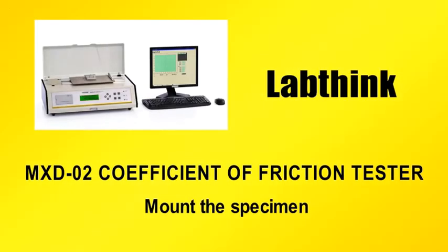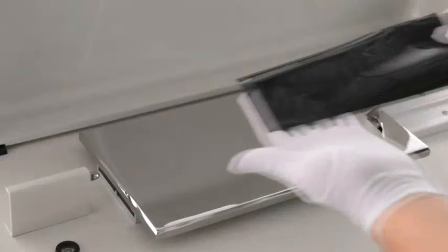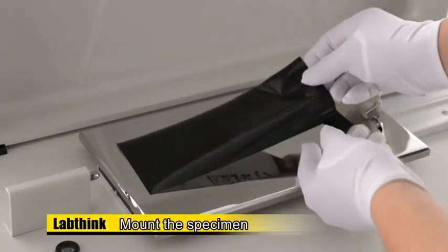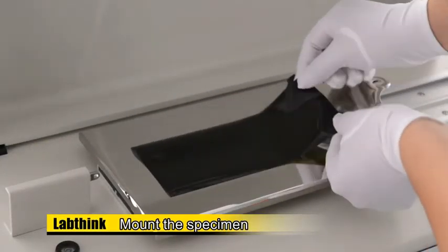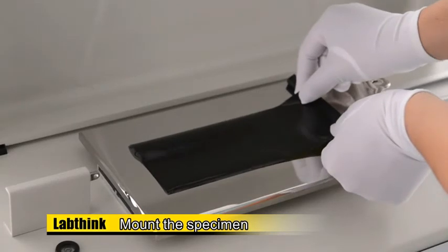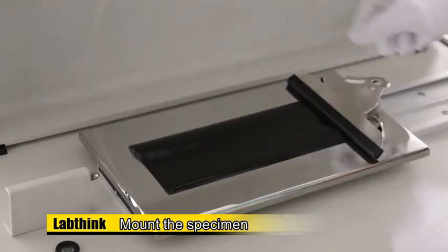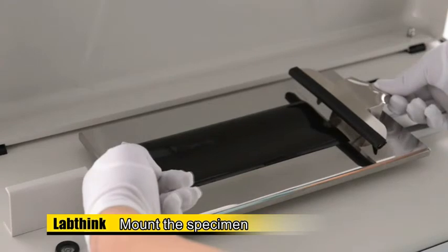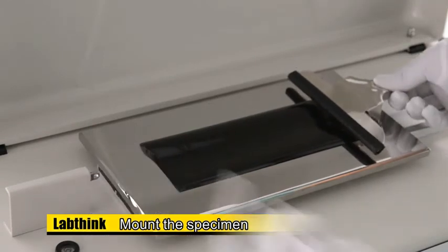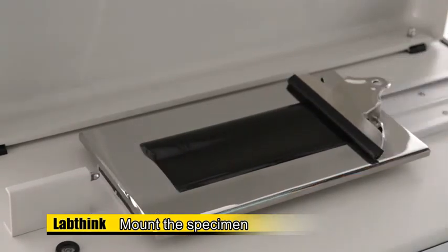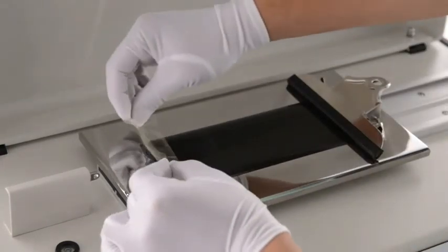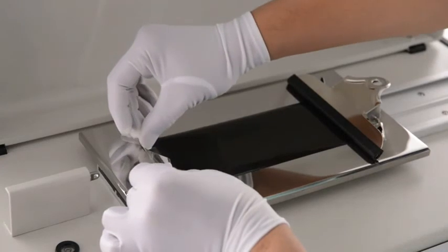Mount the specimen. Put the 200mm by 80mm specimen on the plane with the testing surface upside. Lift up the specimen clamp on the right side of the plane gently and insert one end of the specimen into the clamp. Release the clamp to fix the specimen. Make sure the length direction of the specimen is parallel to the machine direction of the plane. Tape the other end of the specimen on the plane if the specimen is curly.